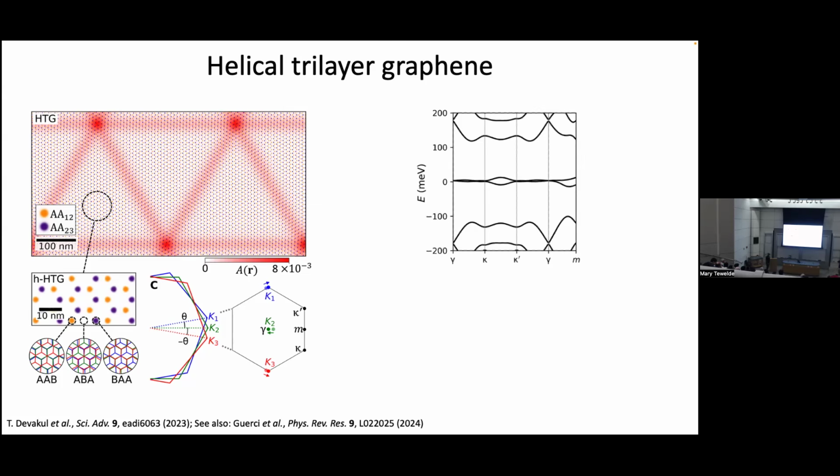So if you imagine a global strain that already does this for you, and you bring your K2 without needing any local relaxation, you bring it to what is effectively the gamma point. That is, you stretch the middle layer isotropically, then what you get is that actually this is already commensurate. So it's equivalent to one of these domains growing to infinity.